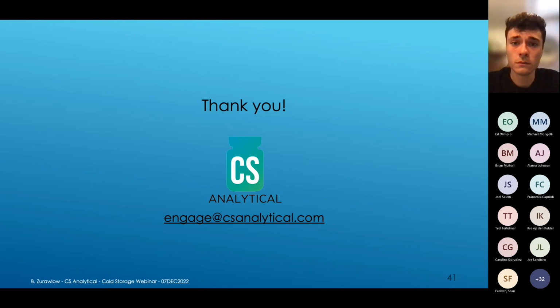Brandon, maybe just a question. Have you seen in particular any issues with the polymeric components, especially with the deep cold storages? Sure. Yes. Long story short, when you're referring to polymeric components, are you referring to things like vials, COC vials specifically? Yes. So the same concepts are relevant for polymeric primary package systems, because really the bulk of what we're seeing in terms of issues at these cold storage temperatures really comes from that elastomer and not so much from the glass, let's say, side of things.